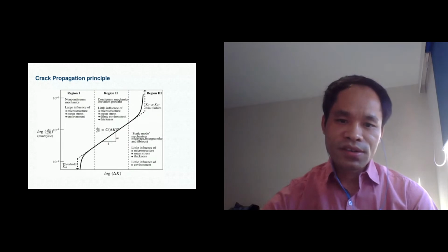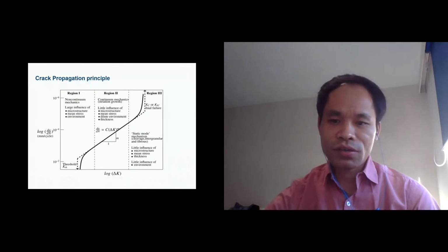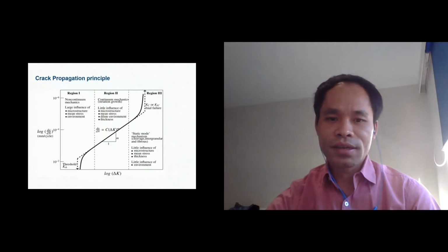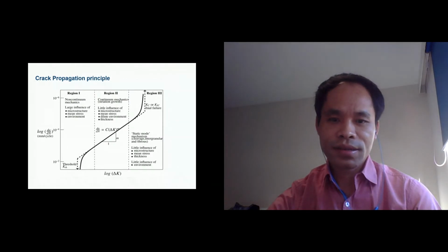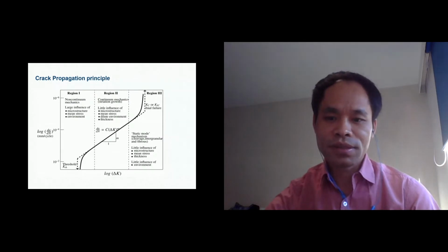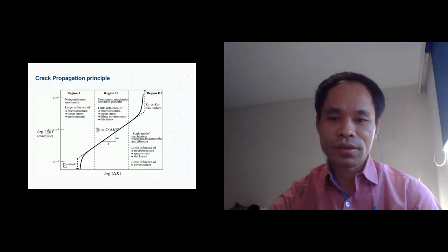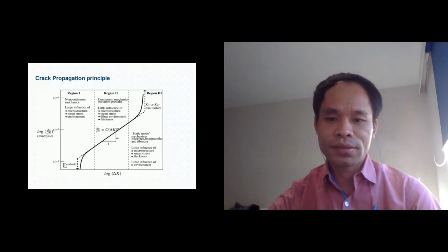But in region 3, the crack growth is abnormal. Why? The reason is that when the crack reaches region 3, there is plasticity development in the material. Because of this, it has rapid crack growth, leading to failure.